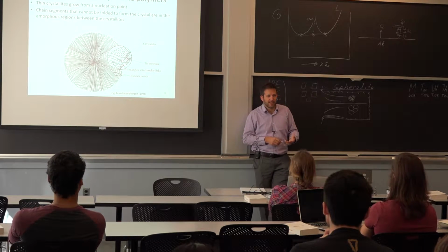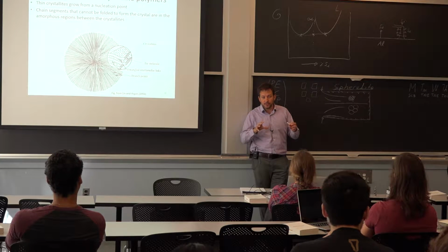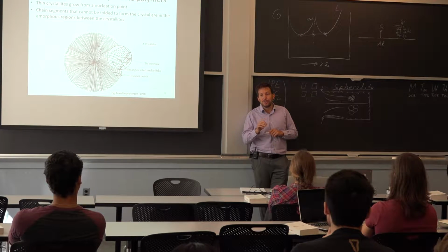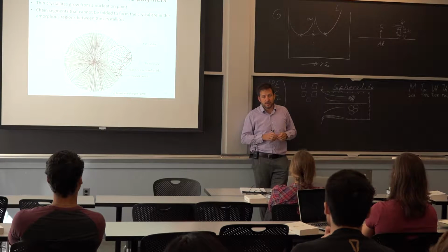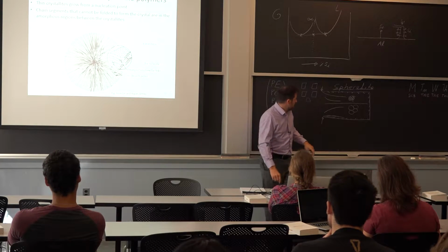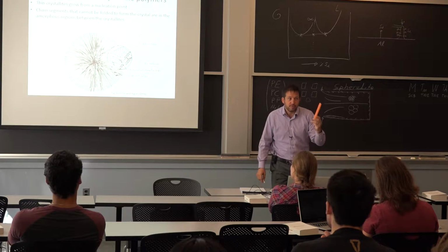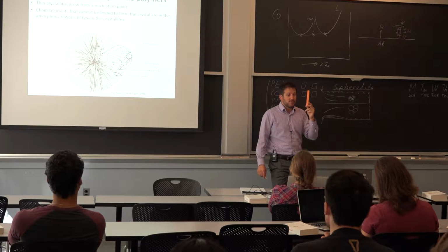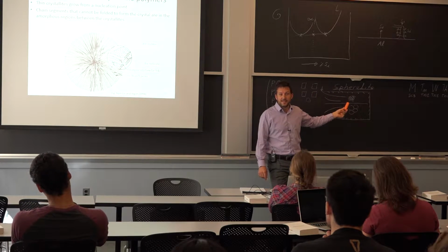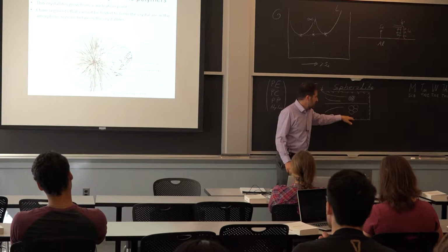So sometimes I forget to mention some of this. If you take an injection molded part and you machine it to make it better in terms of accuracy, a lot of times you will lose strength because you're losing that orientation effect on the surface. Now there's another thing I mentioned. I said, well, we're going to break down these spherulites. That is if we do an extrusion after the fact. If all we do is injection molding, that's it. That's all you get. So you do want to have that skin.